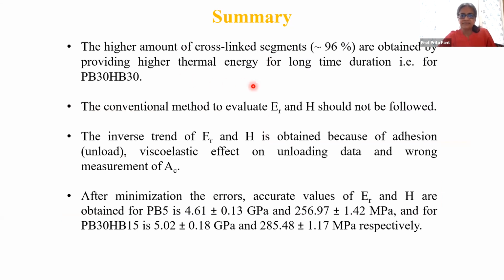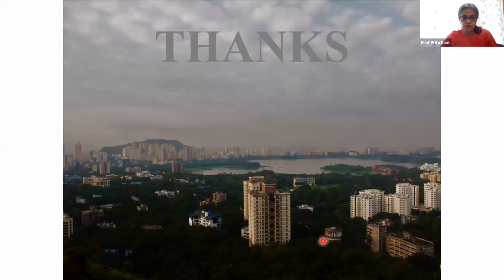I'm just going to summarize the results. You can make these samples, you can pick a system which works easily for you, you can play with cross-linking density. It is good to know the conventional methods very well. It is also good to look at your data and think about it very critically. We could get rid of adhesion, we could get rid of viscoelasticity, and then we had to focus on the calculation of area of contact itself. And once we did that, we are able to accurately calculate the changes in modulus and hardness that occur as a function of cross-linking. The modulus goes up, the hardness goes up as the extent of cross-linking goes up. So with that, I'm going to stop.